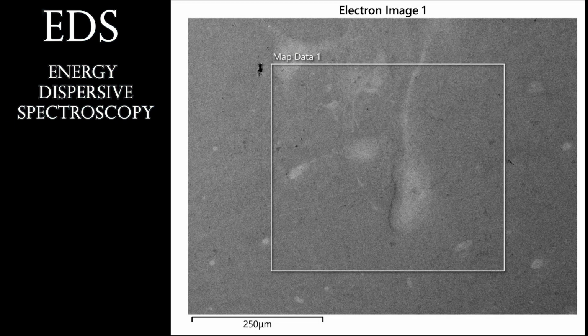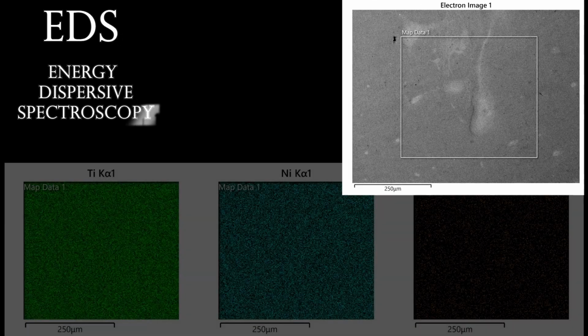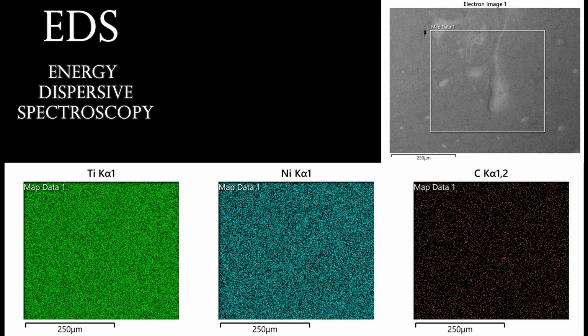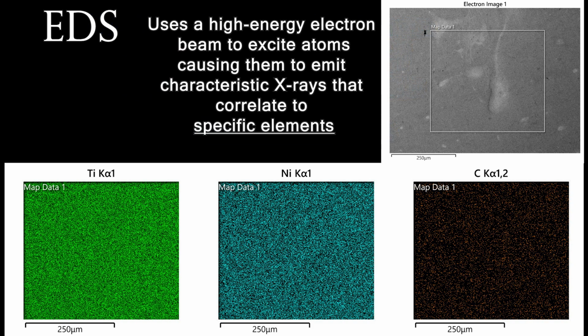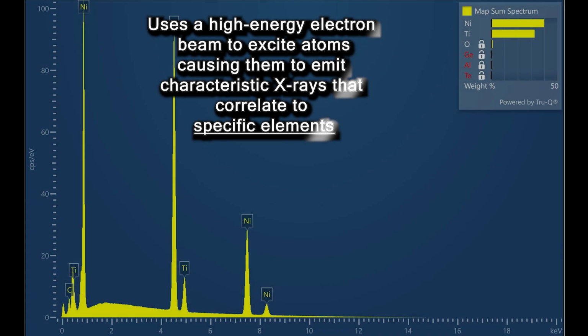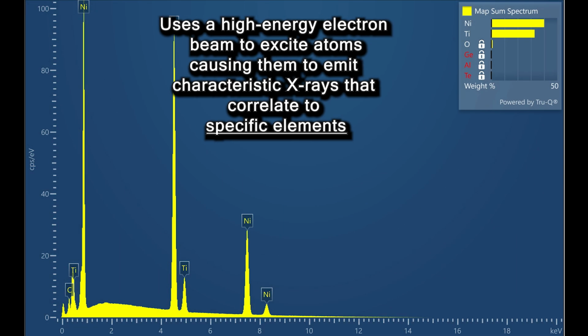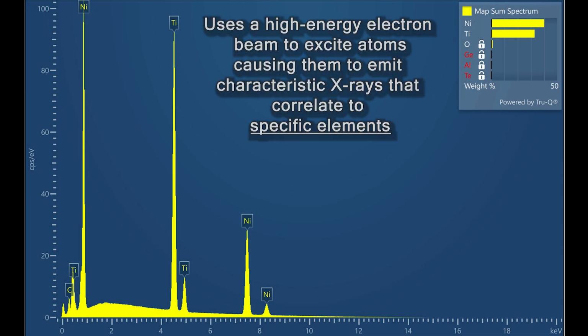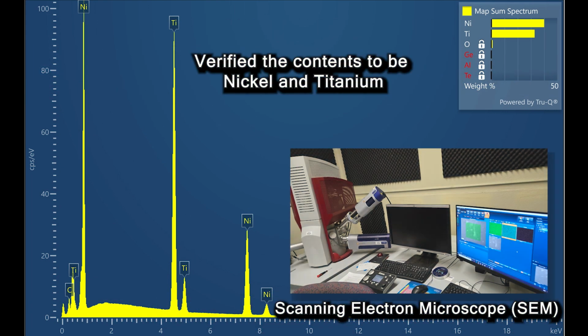Since X-ray diffraction gave us inconclusive data and the thermal bend test cannot precisely determine the composition of nitinol, we used energy dispersive spectroscopy, or EDS, as an alternative method to analyze the material's composition. EDS uses a high-energy electron beam to excite atoms, causing them to emit characteristic X-rays that correlate to specific elements. By doing energy dispersive spectroscopy on the scanning electron microscope, we were able to collect conclusive data of the exact composition of our nitinol samples.